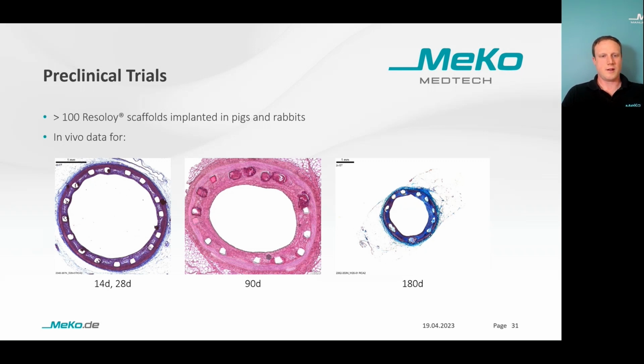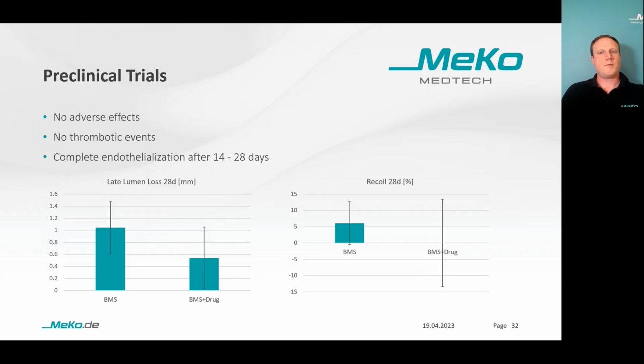Here on the downside, you see histological slices of these time points. During our animal trials, no adverse or thrombotic events were seen, which is in compliance with published data for other magnesium scaffolds. We observed a very fast endothelialization after 14 to 28 days, with a small late lumen loss and almost no recoil after 28 days in vivo, which is a sign of slow degradation and therefore a slow loss of radial force of the scaffold.